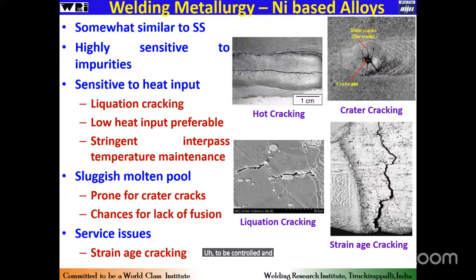And another thing these nickel-based superalloys bring is the sluggish molten pool. The molten pool is highly sluggish, so that means it will not flow. When it is not flowing, it will lead to insufficient filling and can lead to cracks like crater cracks, and also chances of lack of fusion will become more.